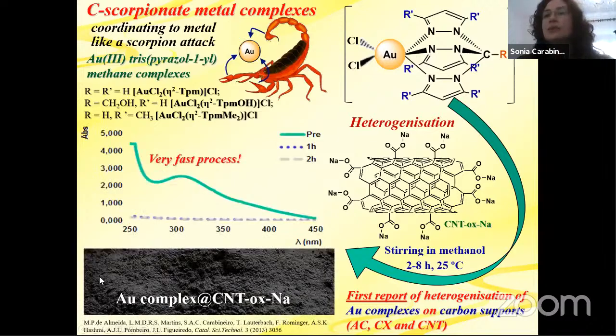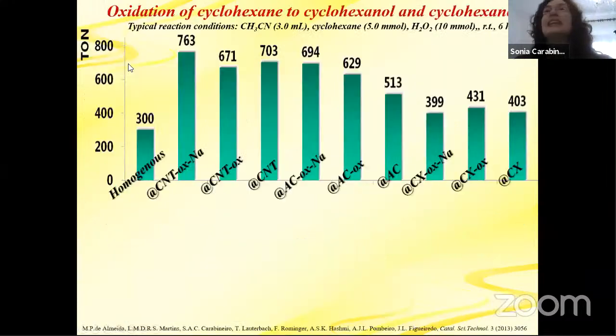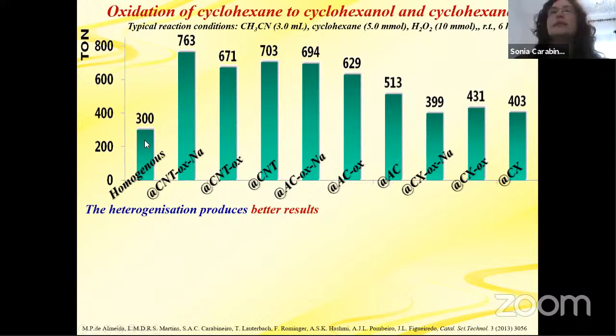And this was the first report of heterogenization of gold complexes on carbon supports. It was reported by us in 2013. Never before had a gold complex been heterogenized on carbon supports. And so we did the oxidation of cyclohexane, the same reaction, here at room temperature for 6 hours. So we see here that the heterogenization produces better results, because here is homogeneous, just the complex itself. This is one of the complexes, and here